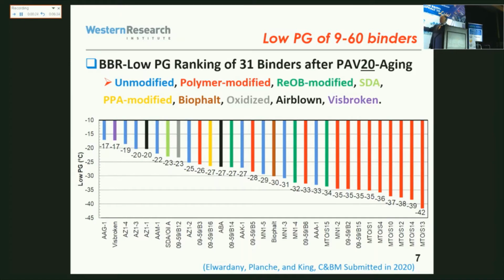And what you can see here is that they are color coded, like all the reds are polymer modified, and you see that they are all performing very well according to the PG grading system. And then you have unmodified, ReOB modified, solvent de-asphalted blends, PPA modified. There is one even biobinder which has no asphalt in it. Okay, it's all bio-based with polymer in it. And then there are oxidized binders and airblown and so on. So you see this type of ranking.